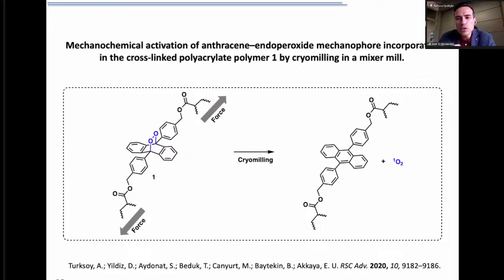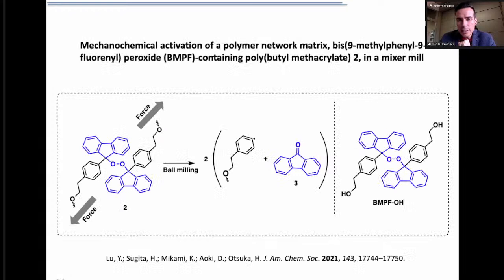Is it the one and only example out there? Well, I found another example published last year in which, once again, there was a polymer that contained a mechanophore. Here we are looking at the mechanophore, which is actually a peroxide. Peroxides are prone to undergo cleavage by homolytic bond cleavage, which generates radicals. When that polymer was subjected to ball milling, the reaction promoted the release of a stable, fluorescent, neutral molecule that was detected. Meaning that by ball milling also, and once again, the force could be transduced all the way to the mechanophore within the polymer.